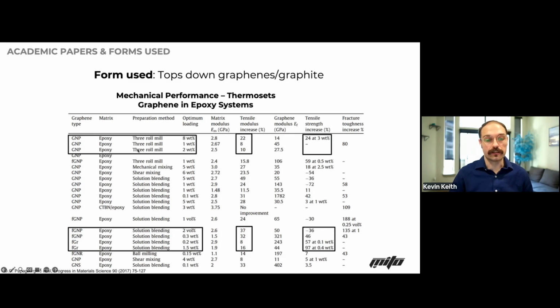So when you go through a standard 3-roll mill method, I would really like to point out here that you'll notice that the GNPs are loaded at a much higher loading, and they get nowhere near as performance values as the functionalized systems or the functionalized graphenes. That's because whenever you try to put pencil lead into a thermoset, even if you're trying to do a 3-roll mill, sonication, whatever it may be, it's still pencil lead.